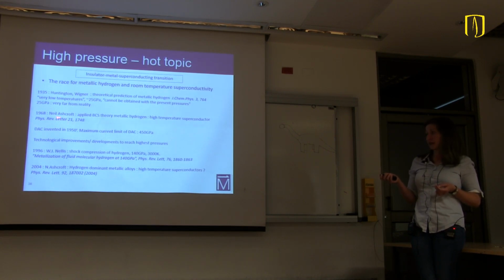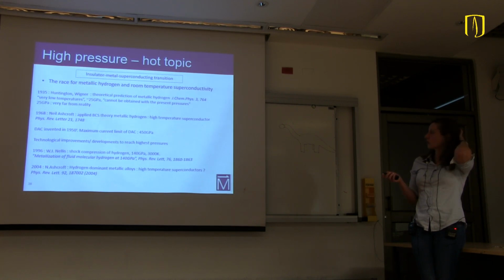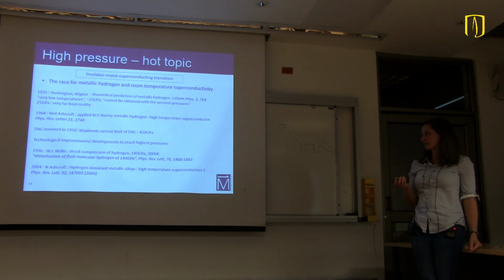Neil Ashcroft, in 1968, pushed that field again. He made the prediction, by applying the BCS theory, the theory for superconductivity, to metallic hydrogen, that metallic hydrogen would become a high temperature superconductor, like really high temperature superconductors. But again, the diamond anvil cells had just been invented. That was really the beginning of real high pressure work.